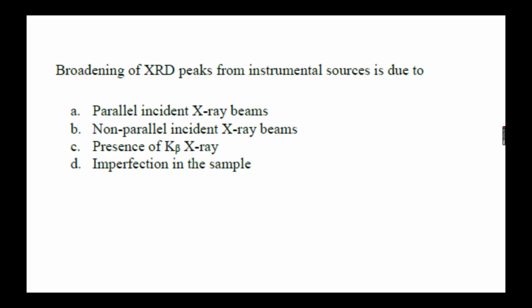Again, it is about the broadening of XRD peaks from instrumental source. Just now I showed a few slides back that due to the instrumental sources, there will be broadening in the XRD peaks. So this is due to what? Parallel incident X-ray beams, non-parallel incident X-ray beams, presence of K beta X-ray, or imperfection in the sample. B, non-parallel incident X-ray beams. Okay. What about others? B. Okay.